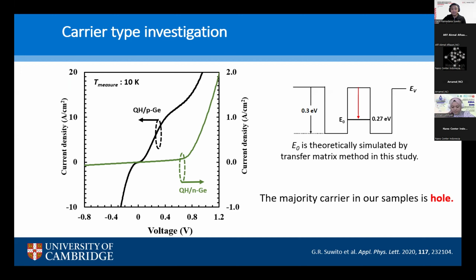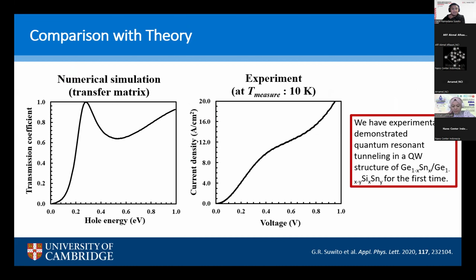Okay, so moreover, the quantum well structure that we designed theoretically suggests that we get the ground state at 0.27. Okay, so this is the complete simulation for the spectra of the transmission tunneling characteristic. And you can see that the TE spectra quite match with experiment, so that you can see the hump at 0.4, then the hump here, and then it suggests that what we observe is using germanium tin based materials.